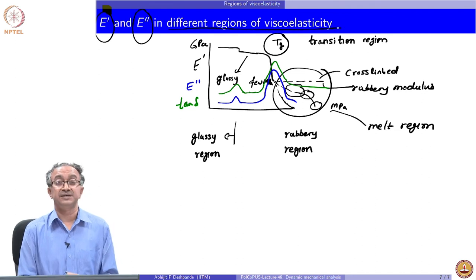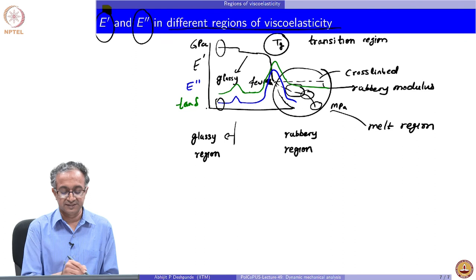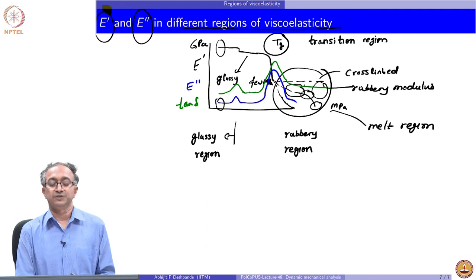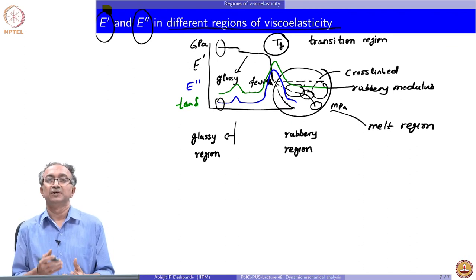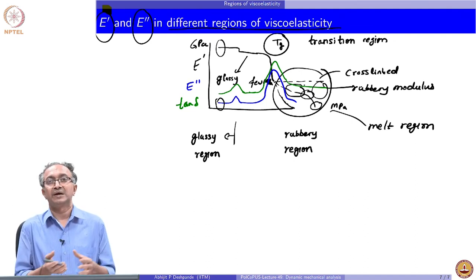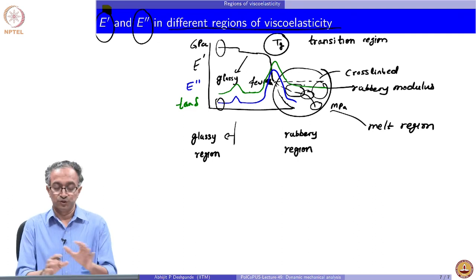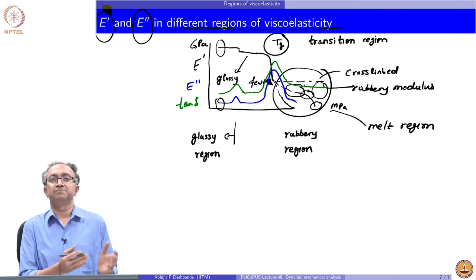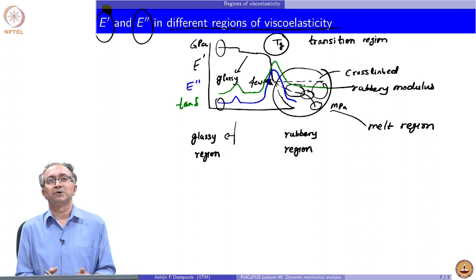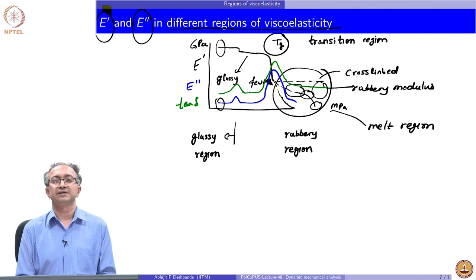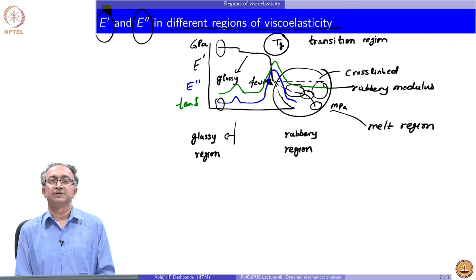Different regions of viscoelasticity can be analyzed using dynamic mechanical analysis. As temperature increases and thermal energy becomes more accessible to macromolecules, more relaxation processes occur and dissipative response is observed, while lower temperatures yield more elastic responses. DMA is an excellent instrument for analyzing viscoelastic response using oscillatory as well as creep and stress relaxation experiments, and is a workhorse for characterizing the overall viscoelastic response of polymeric systems. We will continue our discussion with damping response in one of the next lectures. Thank you.